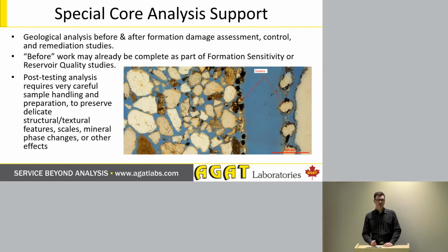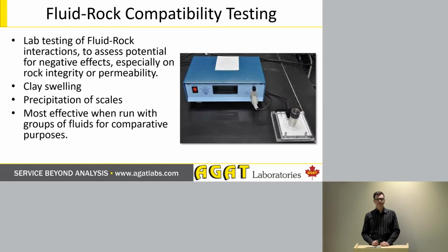In the example in the photo here, we actually have very clear fines migration. We have quite a coarse sandstone, but we've had migration of fines up against the screen that was present in the plug. And we could actually, throughout the whole thin section, see an increase in fines in the direction of throughput. So this was telling us that fines migration may well be a problem in this particular example.